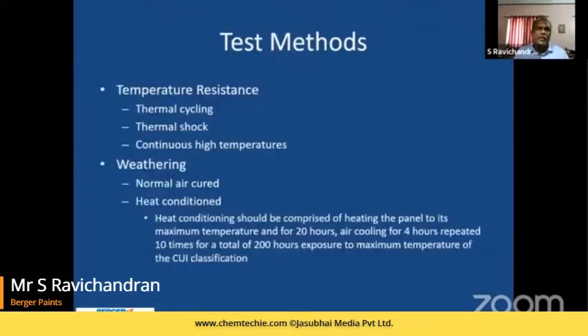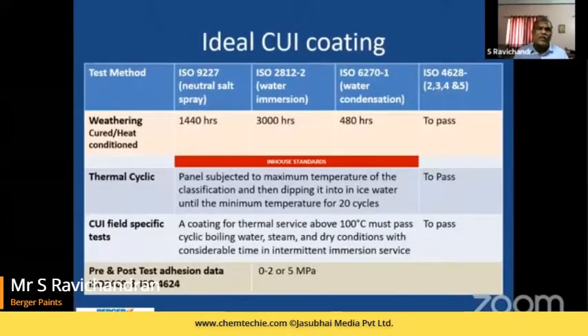The typical test methods for these products are thermal cycling, that is your thermal shock, and giving a higher temperature, lower temperature, and drying it, wetting it, all these different types of tests which are being followed to understand the resistance which it can offer to varying temperatures and operating conditions. And in certain conditions, we need to check the weathering parameters and the heat condition parameters. Now, when you look at the overall summary of all these tests, ISO 9227 or 2812 and ISO 6270 and 4628 have been looked upon as a guiding reference when it comes to the heat conditioned or weathering cured and how many hours it is able to take care of this type of service.